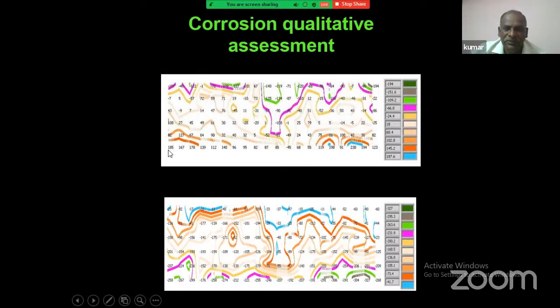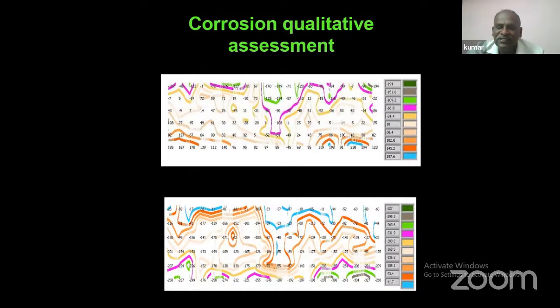For example, these are the qualitative assessments. Number one is open circuit potential. For example, the first graph is completely of open circuit potential. We have done the open circuit potential, and it is compared with the surface potential also. You can see both are almost identical. Only the magnitude is different, but the profile is almost the same in both graphs. So if you are not able to get the reinforcement connection, in that case you can use surface potential using two reference electrodes to make the same survey. Then you can make a mapping, and then you can identify the gray area.